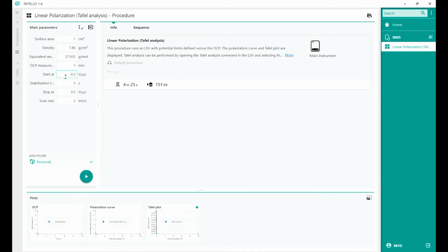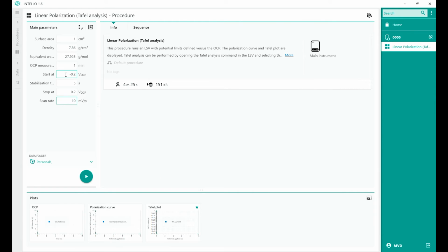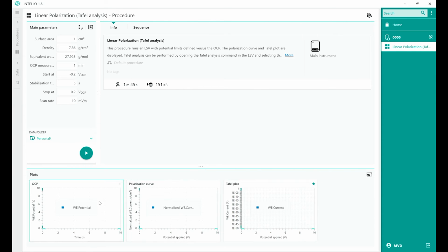First, we're going to adjust the scan rate. It's now set to 2 millivolts a second, and we are going to adjust it to 10 millivolts a second. This is just for speeding up the process. Normally you scan at a very low rate, but in this video, for example, we're going to speed up the process a little bit. And we're just going to scan from minus 0.2 volts versus OCP to plus 0.2 volts versus OCP. And after this adjustment is done, we can increase the plots, polarization curve and Tafel plot.